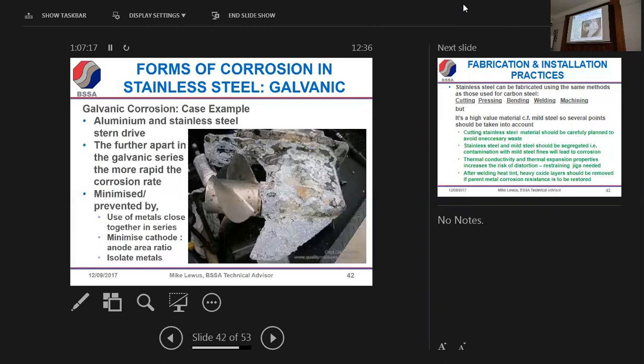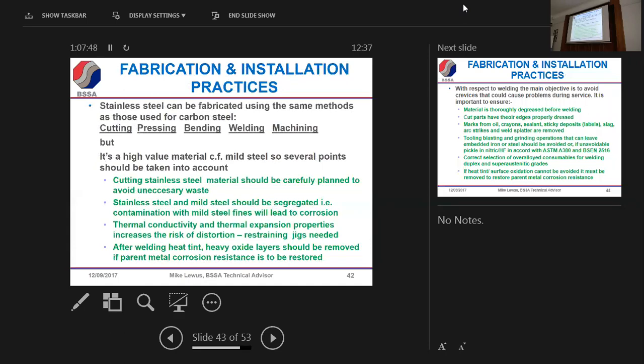An example is a stern drive, aluminium and stainless steel. The rule usually is don't put aluminium and stainless steel together, particularly if the aluminium has got a small surface area relative to the more cathodic material, the stainless steel. Because if the cathodic area is big, the current driving the corrosion is concentrated over a smaller area, so you'll lose material section thickness quicker. So there are some very straightforward rules on avoiding it.